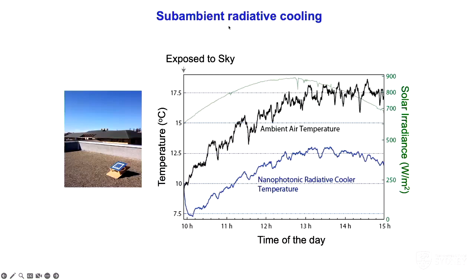The black curve is the ambient air temperature, and the blue curve is the temperature of the radiative cooler that we constructed. This is under solar irradiance, the amount of sunlight around noontime, hitting the sample at about 900 watts per meter squared. In spite of this solar irradiance, this structure has a temperature about 5 degrees Celsius below the ambient air temperature. And this is done entirely passively, without any energy input.